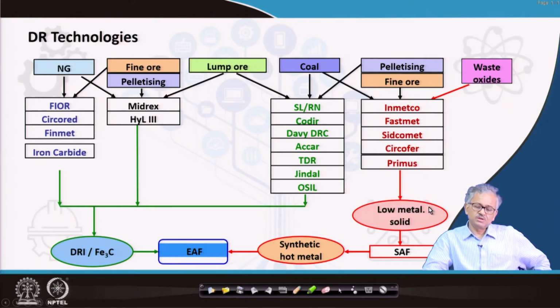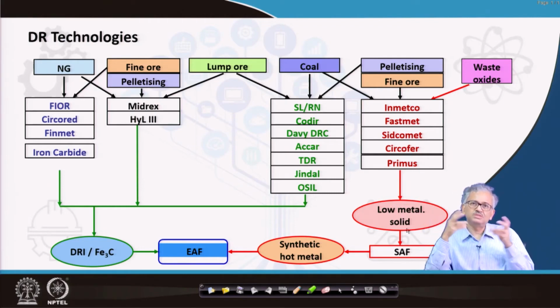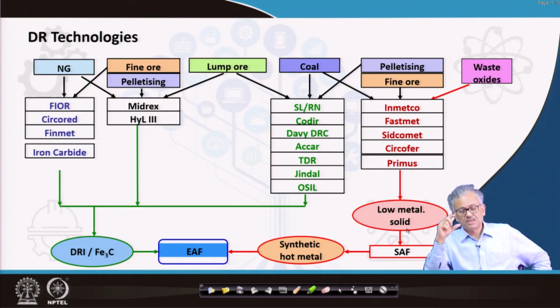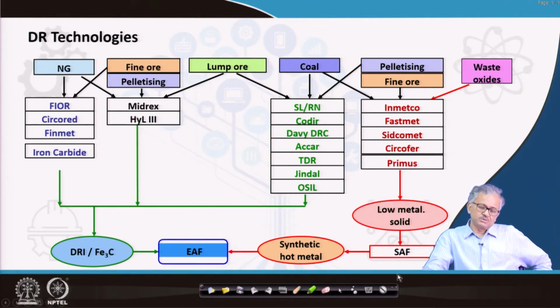In this process you are using the waste oxide, and you are not keeping it for a longer time. You are producing first and getting the low metallized solid, and then you are melting it in a submerged arc furnace, because it contains a lot of gangue material, so it will generate a lot of slag. The gangue has to be separated in the form of slag, metal separation, a lot of slag will form. That's why it is better to use a submerged arc furnace, and then you can separate the gangue.